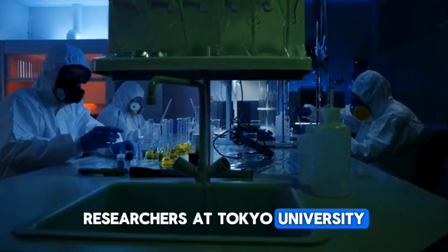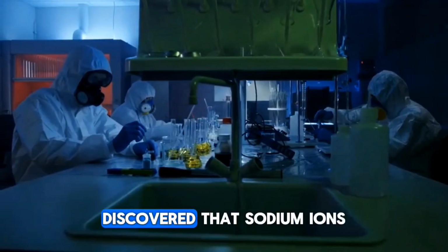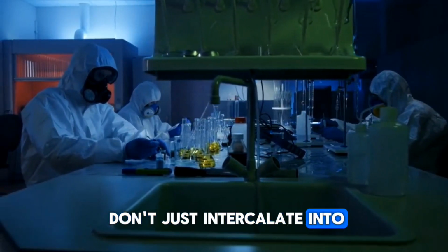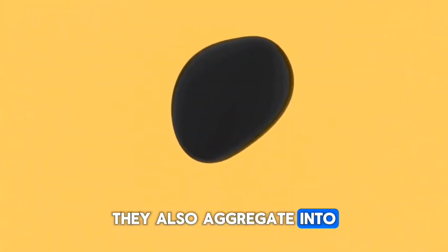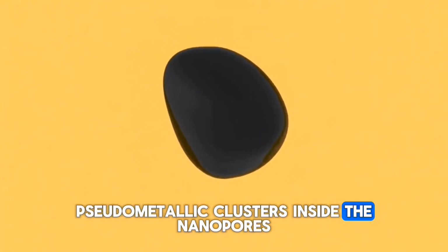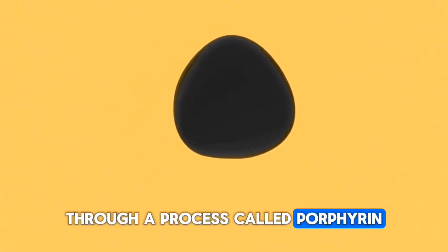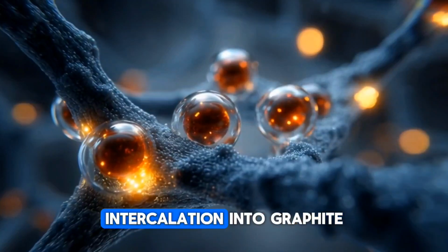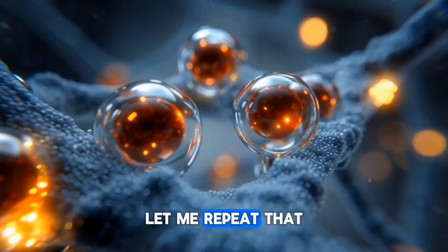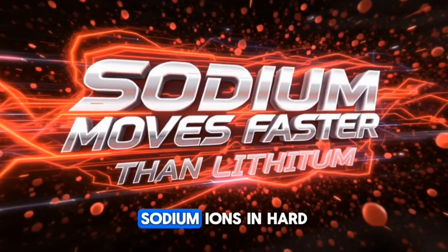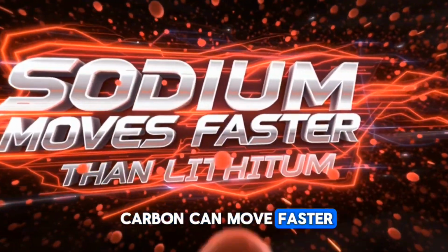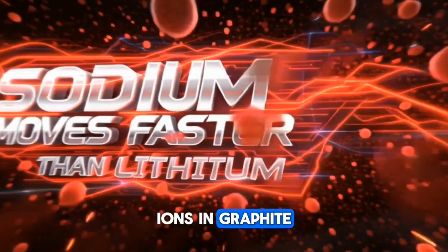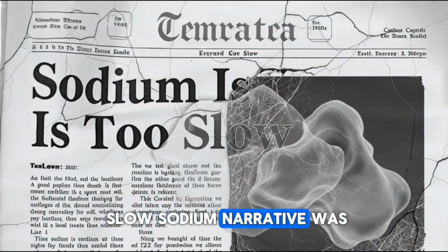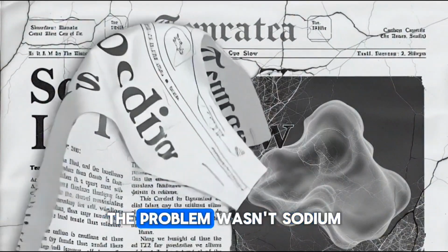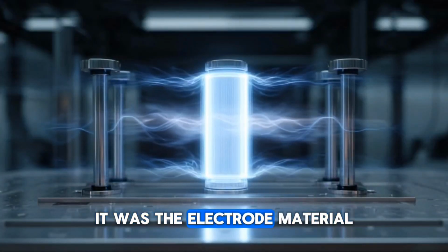Researchers at Tokyo University of Science and Novonix discovered that sodium ions don't just intercalate into hard carbon, they also aggregate into pseudo-metallic clusters inside the nanopores through a process called pore filling. And this pore filling mechanism is intrinsically faster than lithium intercalation into graphite. Let me repeat that, because it's critical. Sodium ions in hard carbon can move faster than lithium ions in graphite. This meant that the slow sodium narrative was completely wrong. The problem wasn't sodium, it was the electrode material.